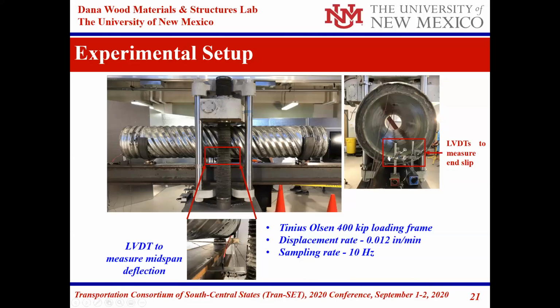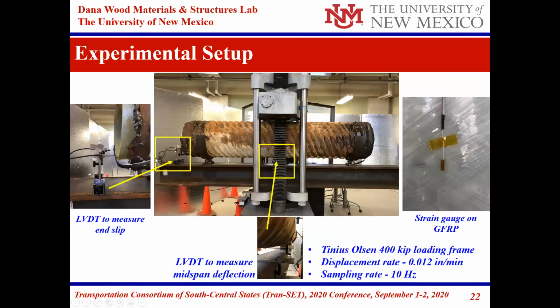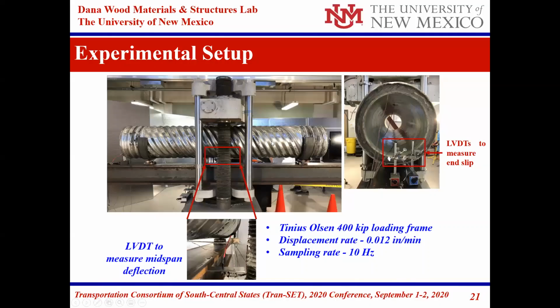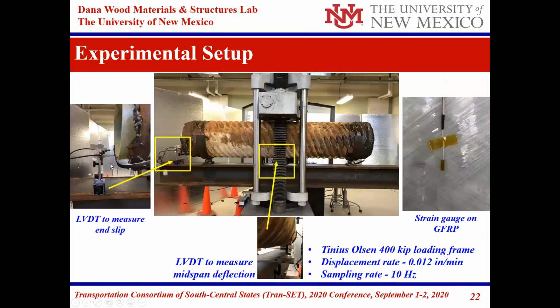This is the case for the non-corrugated pipe retrofitted with the GFRP. And this is a very similar test done for the case of the corrugated pipe, also retrofitted with the GFRP, with the LVDTs, with the strain gauges, everything in. And we put strain gauges inside.